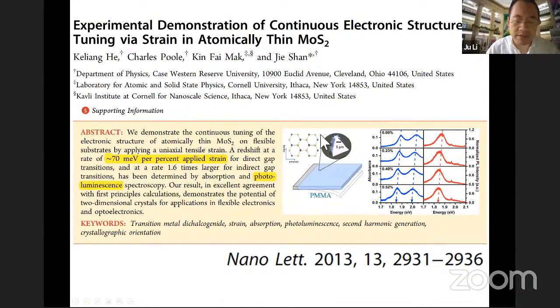And then there were some experiments. So a year later, people put MoS2 onto this polymer PMMA and they bend it. And on the tensile side, you're going to basically apply tension to that monolayer MoS2. And even though the amount of strain is not big, it's only 0.5%, we see there is a visible shift in the photon absorption as well as the photoluminescence spectrum. And the measurement is 70 milli-electron volt per 1% of strain. And the calculation was like 100 meV per 1% of strain. But in this experiment, this is only uniform tensile strain. There is no strain gradient as we predicted.